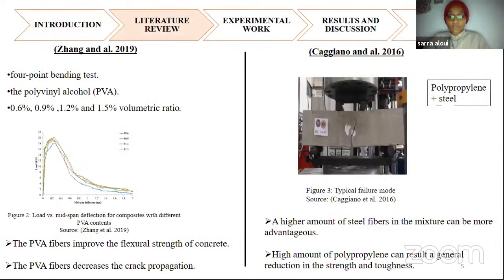In the literature review part, 2 articles will be presented. The first one was done by Zhang in 2019, where specimens with the usage of PVA were tested under a 4-point bending test with different volumetric ratios, from which we could conclude that PVA fibers can improve the flexural strength of concrete, and PVA fibers can decrease the crack propagation.